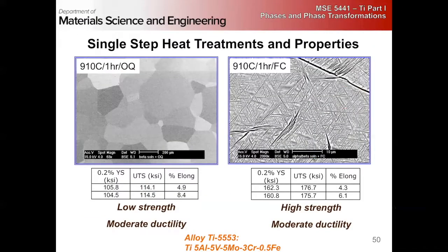All right, the other strategy is to come up with multiple step heat treatments. And of course, the single step, as we had talked about, again, this is in 5553. We showed that oil quench is definitely fast enough to keep you 100% beta structure, whereas the furnace cool gives you a large basket weave type microstructure.